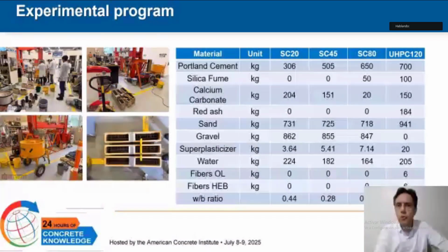The fourth mix corresponds to ultra-high performance concrete and was designed with a water-to-binder ratio of 0.18, a high cementitious content, and the addition of silica fume, red ash, and 2 types of steel fibers. Notably, the UHPC mix eliminates coarse aggregate, relying instead on particle packing and fiber reinforcement to ensure mechanical performance and matrix densification. All mixes were proportioned by mass per cubic meter to ensure proper casting in RILEM beam molds.